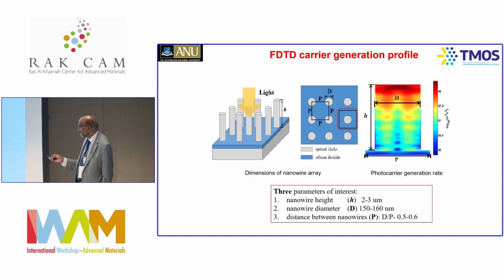Again, we do a lot of simulations looking at what the height and diameter of the nanowire should be, and what the distance between the nanowires should be. It turns out that most of the current is generated at the tip of the nanowire, indicating they don't need to make very long nanowires; only 2 to 3 microns is sufficient. And the diameter should be somewhere between 150 to 160.